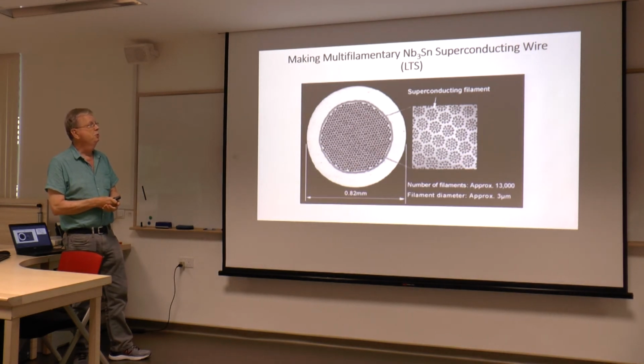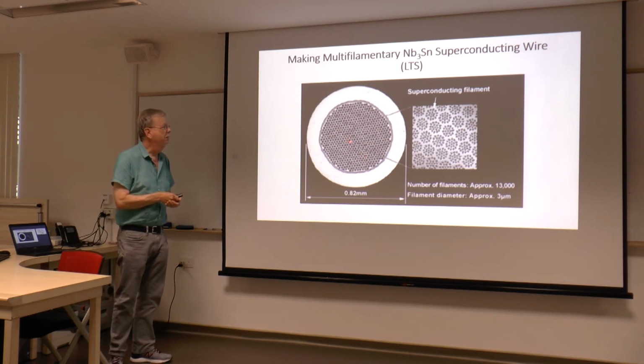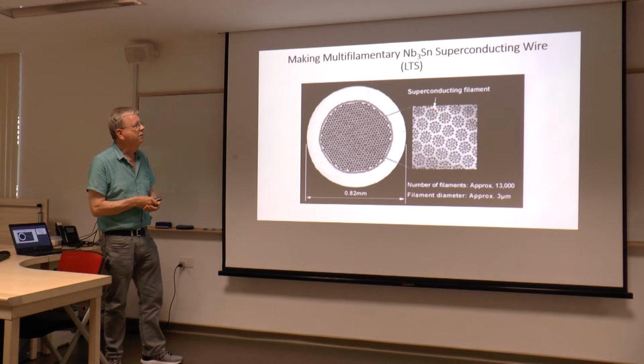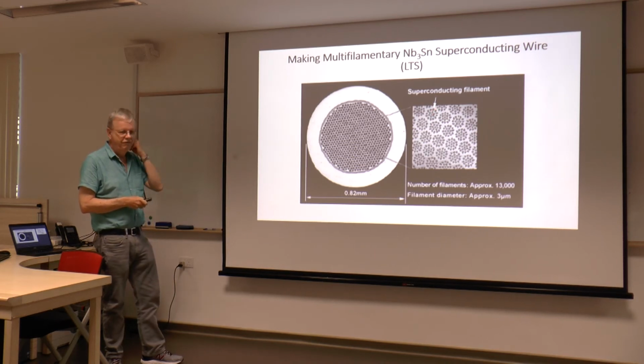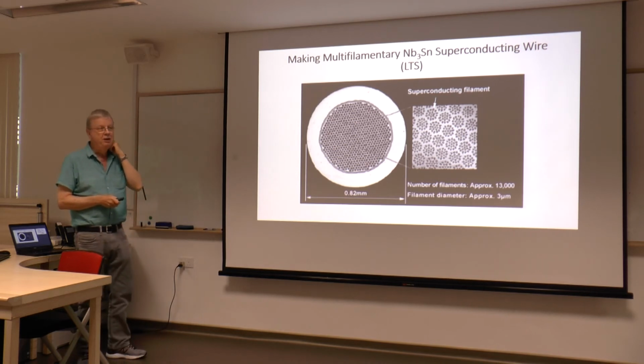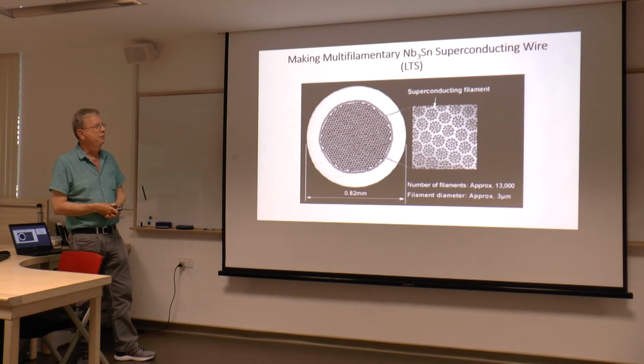Now, just to show you what the low temperature superconducting wire looks like, this is something you can physically see with your eye. And in one of these bundles, it looks like this. So here's a bunch of superconducting filaments. It's a very tricky process, but people have been making A15 niobium tin wire for a very long time, and they have all the tricks figured out. When you draw the wire down, you can't have A15 material present because it's brittle. Except for niobium titanium, any superconductor you're going to talk about is brittle. They're all brittle. If you put them in a silver tube, okay, you can get away with it, but no one wants to do that commercially.